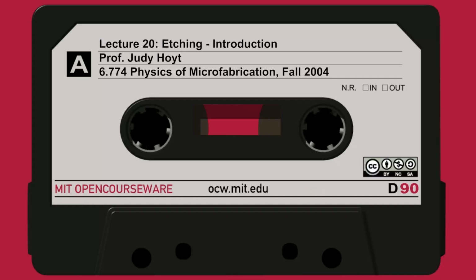Oh, on slide 24 is just an example of a photograph. This is a very old-fashioned, way back 20 years ago, but still found in some labs, Applied Materials 8100 dry etcher. This gives you anisotropic etching, this particular one, of films like silicon nitride, silicon dioxide, and polymer layers. You can relatively control the oxide slope, the slope angle of the contact hole, by using sidewall polymer deposition, just like we talked about in that example of the inhibitor layer. The inhibitor layers are typically polymers. Sometimes people will call them sidewall polymers.